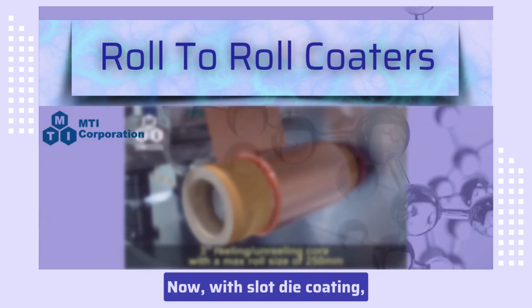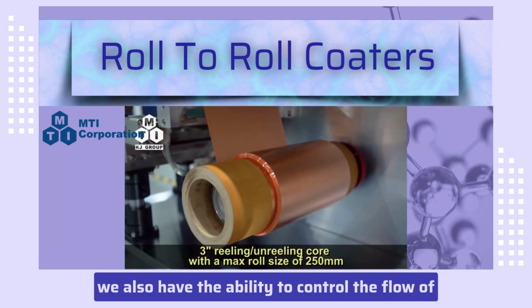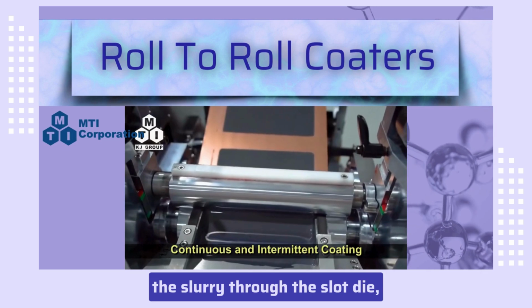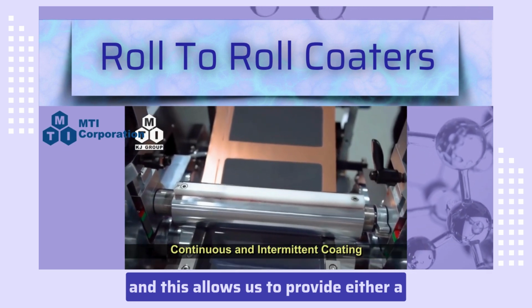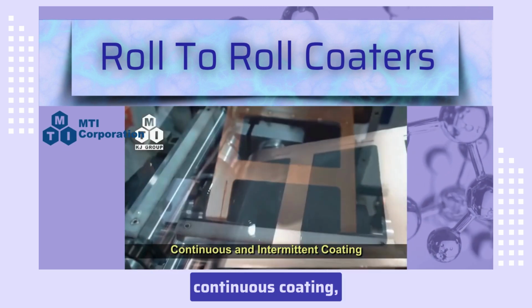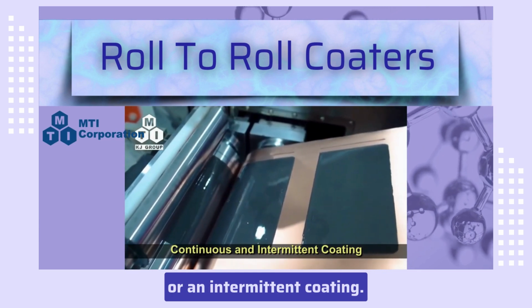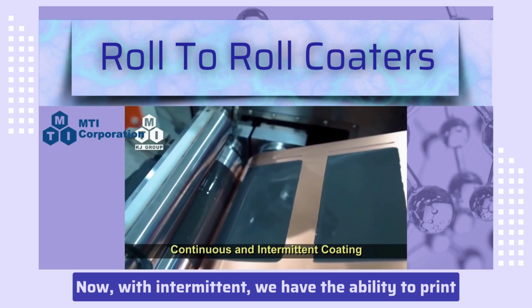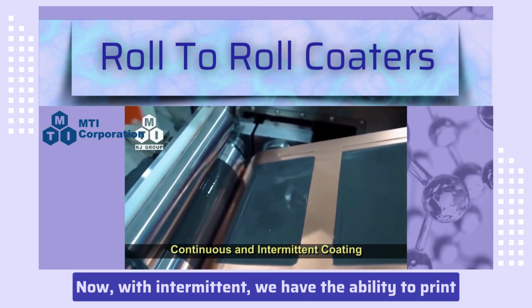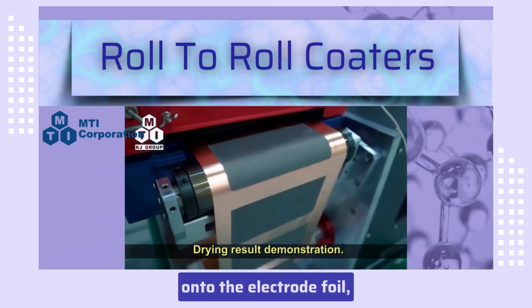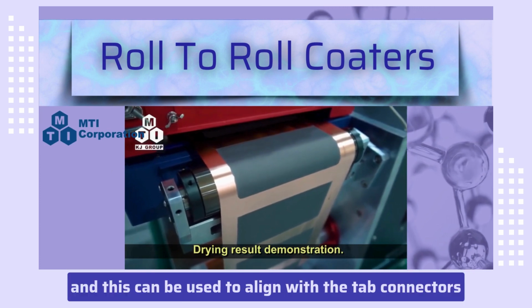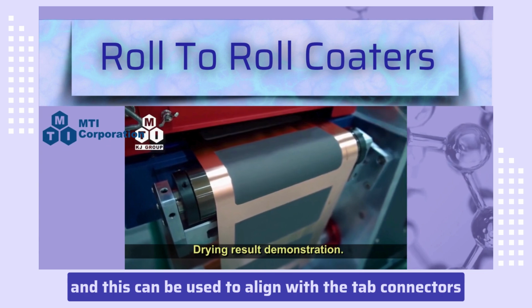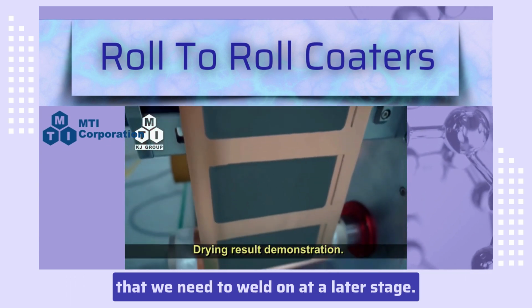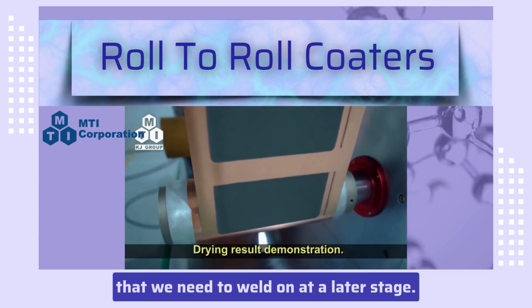Now, with slot die coating, we also have the ability to control the flow of the slurry through the slot die. And this allows us to provide either a continuous coating or an intermittent coating. Now with intermittent, we have the ability to print a defined pattern onto the electrode foil, and this can be used to align with the tab connectors that we need to weld on at a later stage.